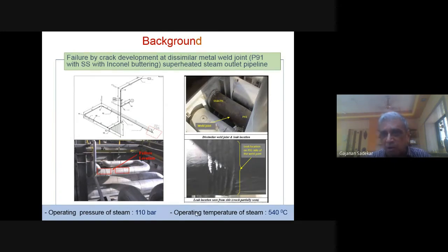What was coming out of the reformer, now the steam was flowing through this, sorry, the steam superheater line. Steam was coming out from the reformer, and the major pipe which was coming out initially was a stainless steel, and afterward the steam pipe was P91, that is a chrome alloy steel. Now this joint, the stainless steel was welded to the alloy steel, but with a particular joint. I'm going to show the configuration of the joint.